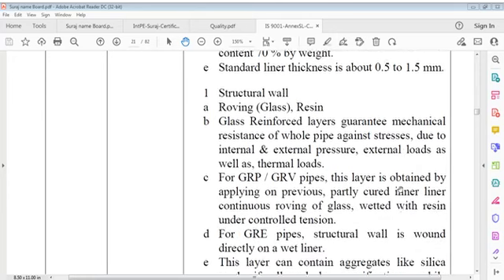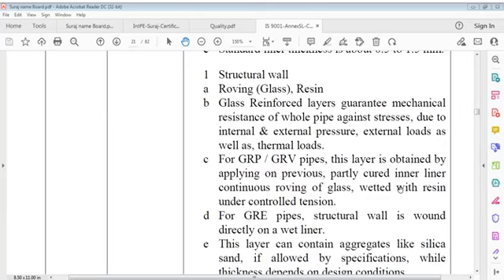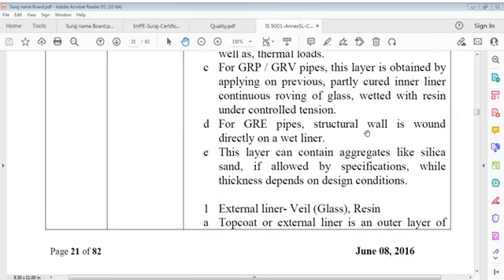Structural wall, roving glass, resin: glass reinforced layers guarantee mechanical resistance of the whole pipe against stresses due to internal and external pressure, external loads as well as thermal loads. For GRP/GRV pipes, this layer is obtained by applying continuous roving of glass, wetted with resin under controlled tension, on the previous partly cured inner liner. For GRE pipes, the structural wall is wound directly on a wet liner. This layer can contain aggregate like silica sand if allowed by specifications, while thickness depends on design conditions.